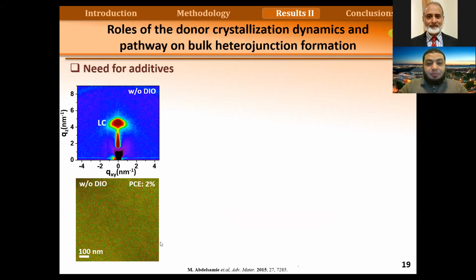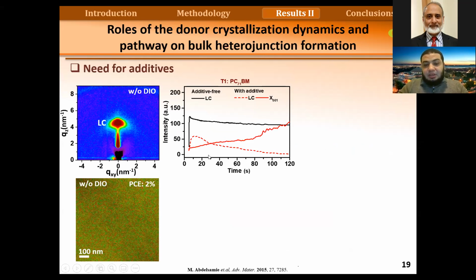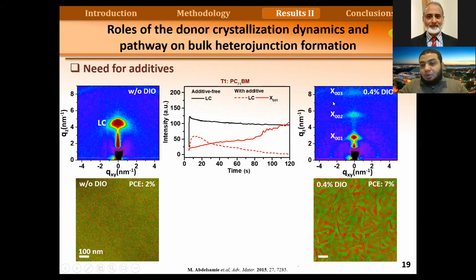As we can see here, if we process a material without additives, here on the left, we get a liquid crystalline phase. The red color and blue color are for the donor and acceptor materials. As we looked at the processing in situ, without additives, the material is trapped in the liquid crystalline phase, but with additives we can dissociate the liquid crystalline phase and form the crystalline phase. If we process with additives, here on the right, we can form the highly crystalline phase during spin coating, and we also have larger phase separation.